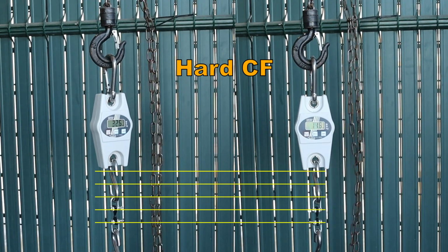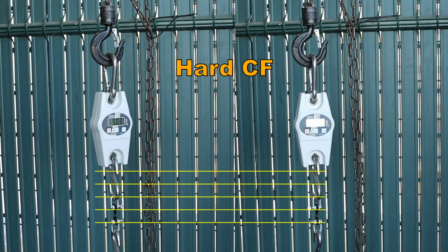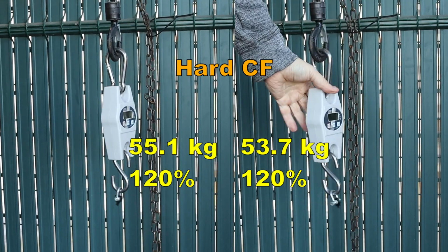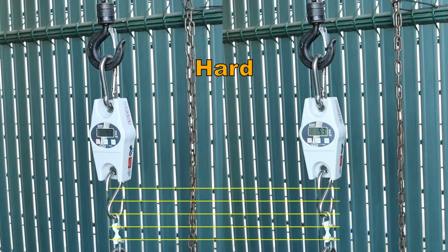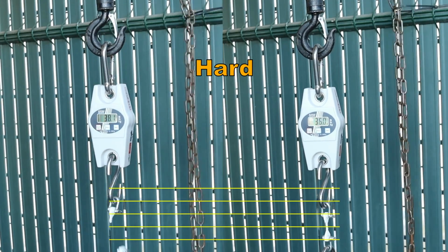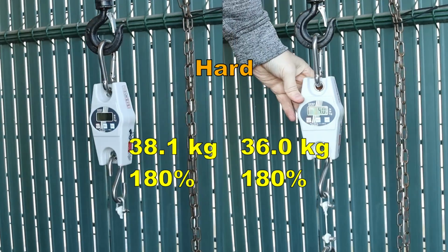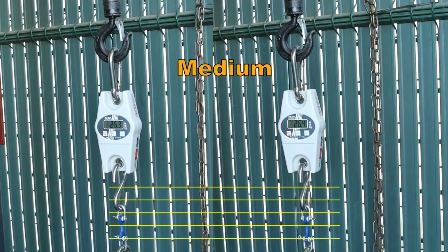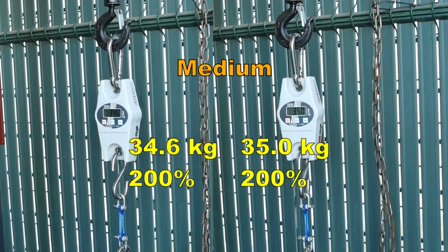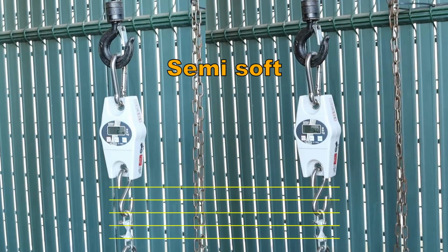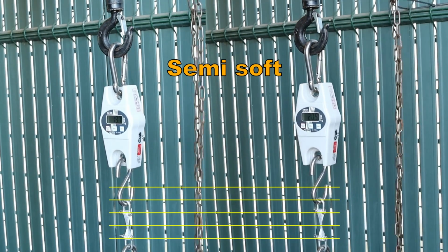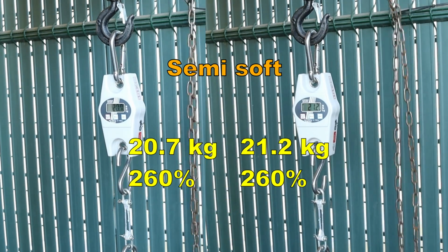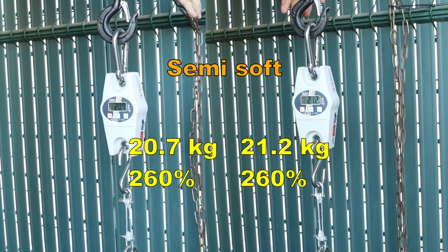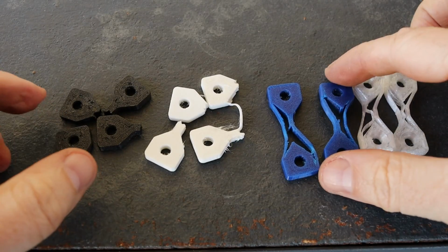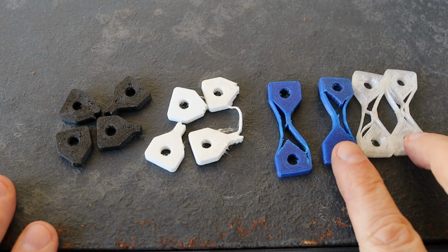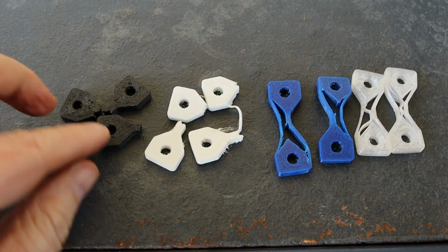This is the pulling test where I want to record the brake load, but also I want to record the maximal length before the brake. And now this is the hard without carbon fibers. The medium, and it failed inside the test objects, and very similar failure I can see on the semi-soft. On 2 soft materials the inner wall snapped first, but on carbon fiber version it broke completely on the smallest cross-section area.